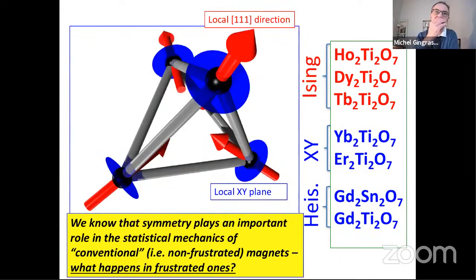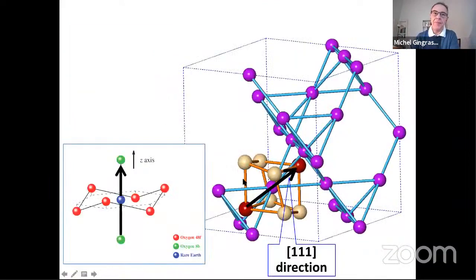So this is an illustration of what I mean. If I focus on one tetrahedron unit forming this pyrochlore lattice, the anisotropy is such that the magnetic moment likes to point along these directions, from the center of one tetrahedron to the center of the other, as indicated by this black arrow here.